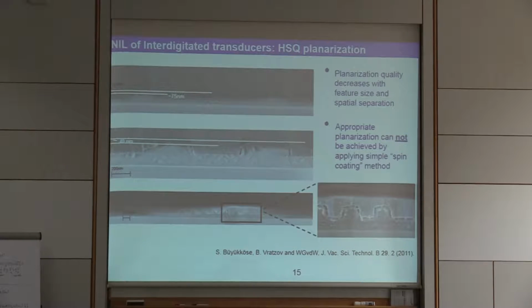So the results, it's maybe not so easy to see, but here you see the imprinted features. There is somewhat of a planarization, but still, here it says 40 nanometers, some variation on top. Here also you can see that it's not really fully planarized. And again, the degree of planarization depends on the features there. If you have larger feature size or larger spatial separation, this planarization gets worse.